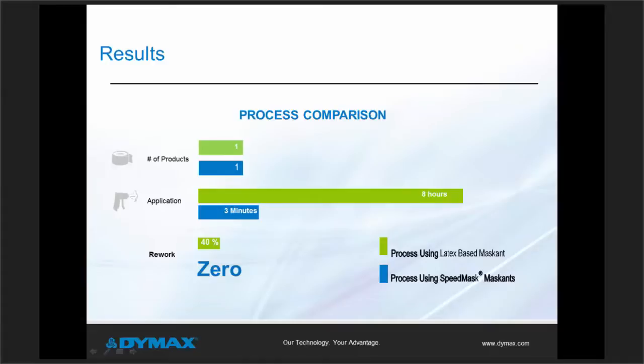This customer had been using a latex-based masking to protect the connectors and adjacent areas on the printed circuit board. This masking had a drying time of 8 hours, whether it was 1 or 100 boards. Labor savings were a direct result of on-demand cure and achievement of zero keep-out area violations. The reliability of this masking reduced keep-out violations to zero, eliminating the conformal coating rework process. The rework was reduced from 40% to zero. This solution helped this company meet the 30% productivity demand increase while also reducing their overall operating costs.